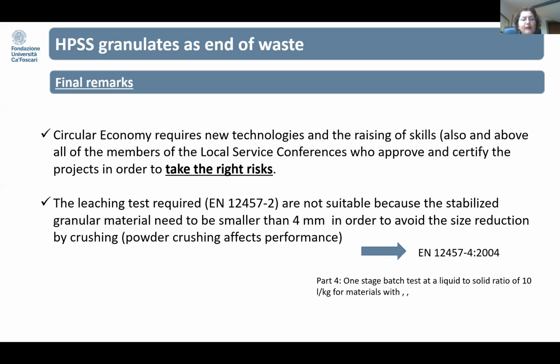We have the last remarks regarding the leaching test required. That is, as in Italy we perform for the waste, is the EN 12457, part 2, that is not suitable because the stabilized granular material needs to be smaller than 4 millimeters in size, in order to avoid size reduction by crushing. Then, as you can imagine, powder crushing affects the performance of the leaching, of course. So we suggested to perform part 4 of this test next time.